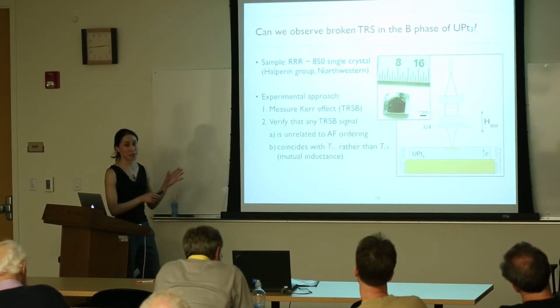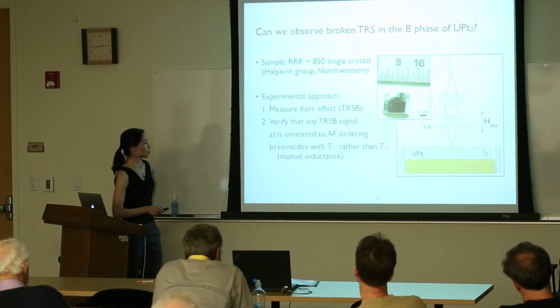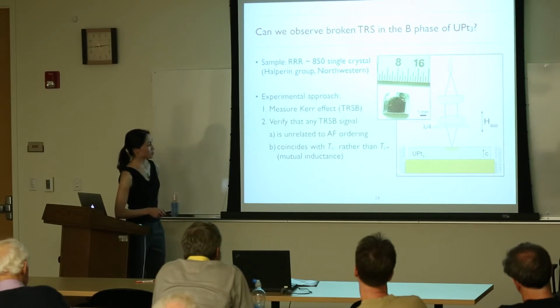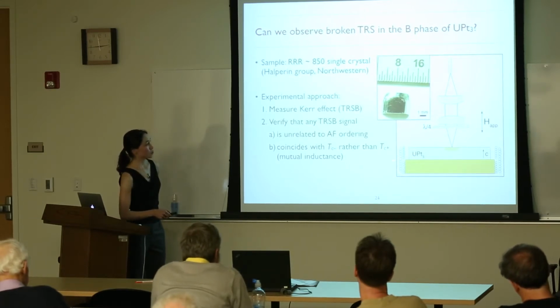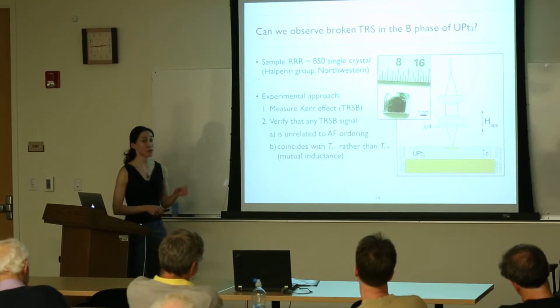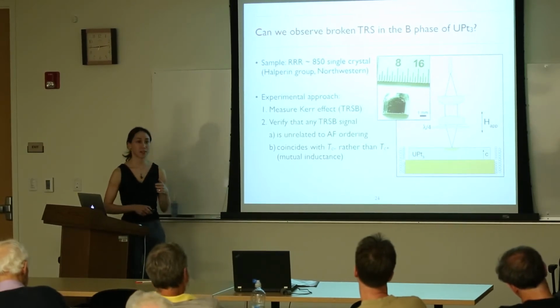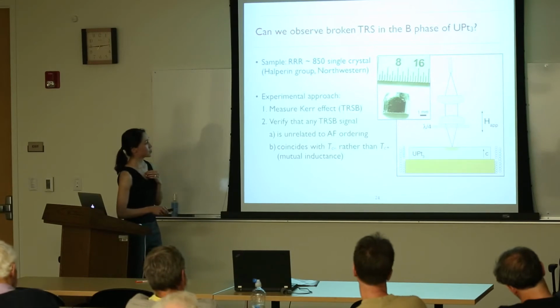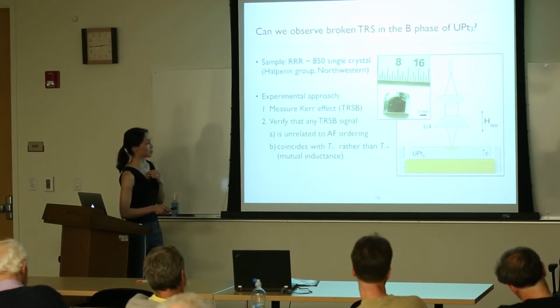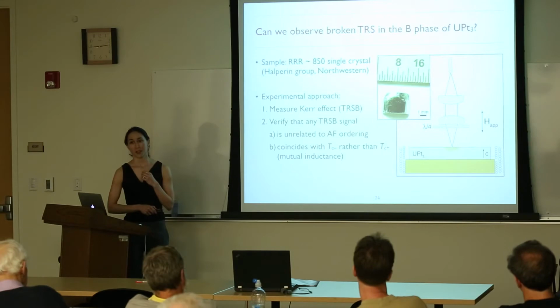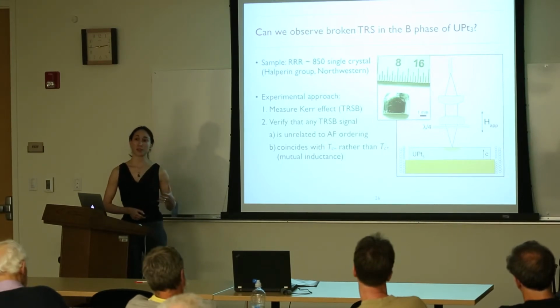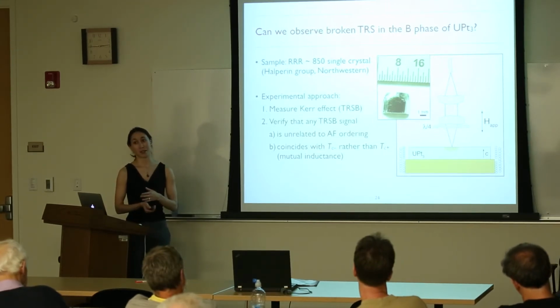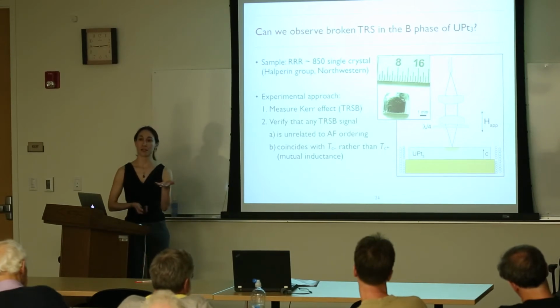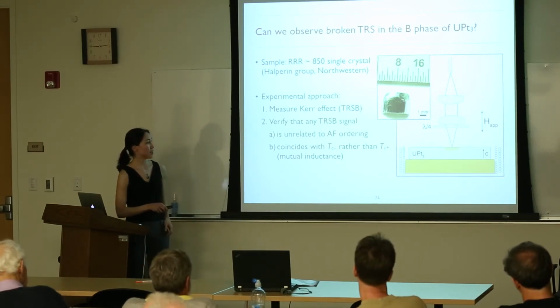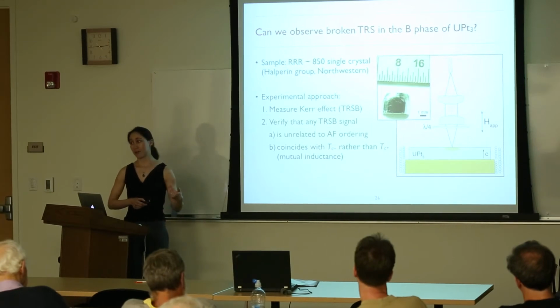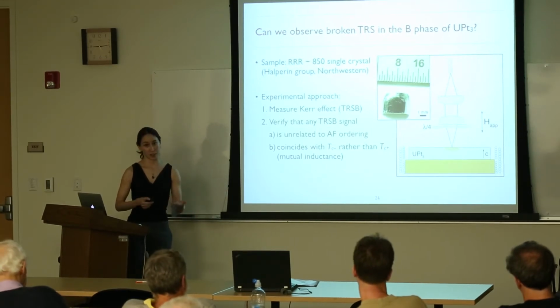So in order to try to tease these two temperatures apart, we also measure mutual inductance, which is basically you wind a coil around your whole sample. You use that to apply a small AC magnetic field, and then you measure the response of the sample with some inner counterwound coils. The idea being that once the material goes superconducting, it will start to try to expel the fields that you're applying to it. That can be picked up here, and so that will be a good way to identify TC just in the bulk.